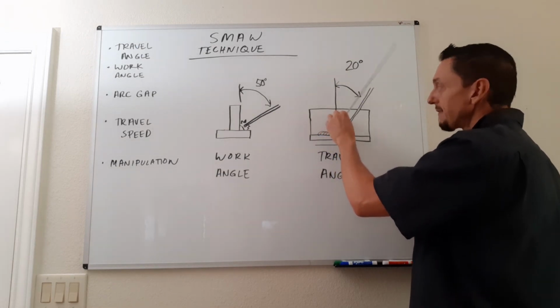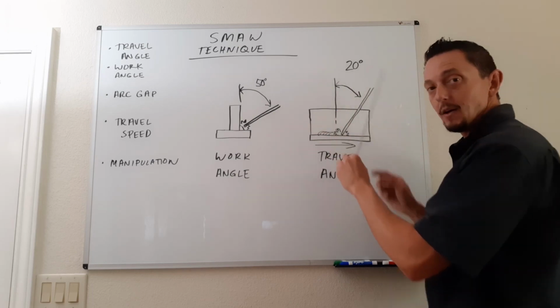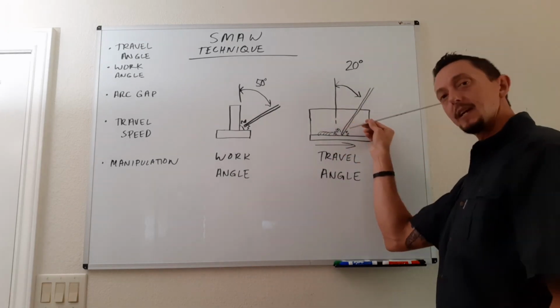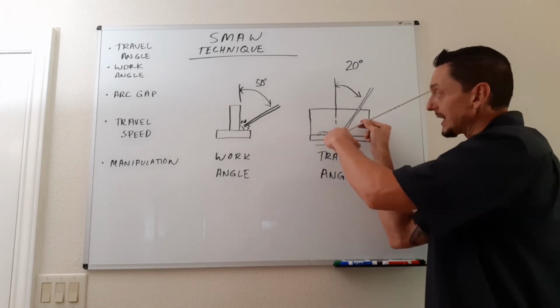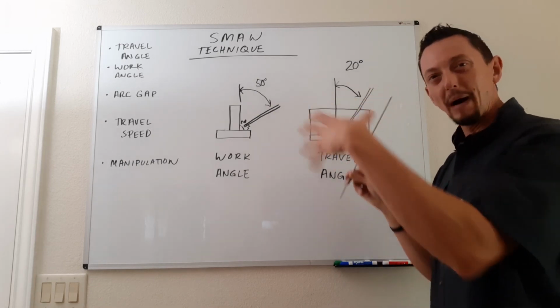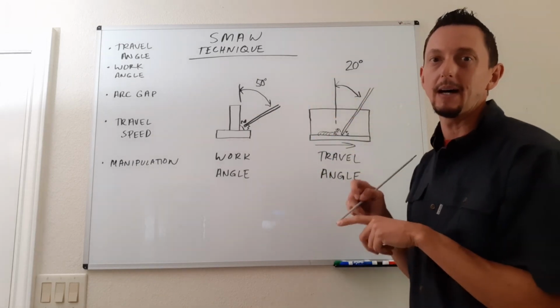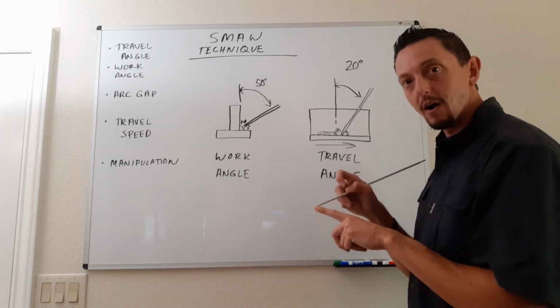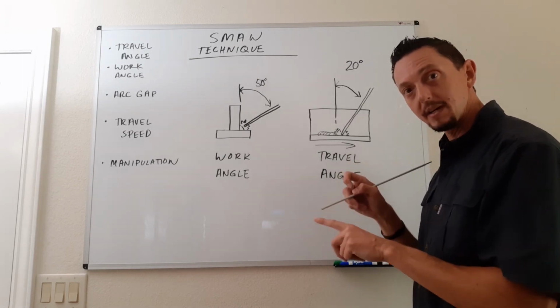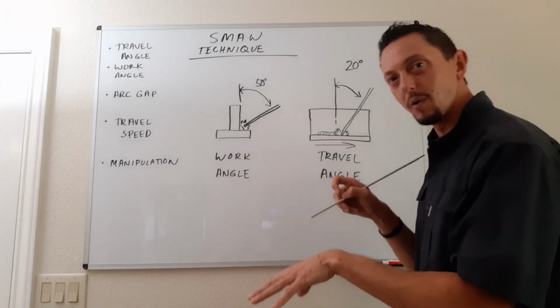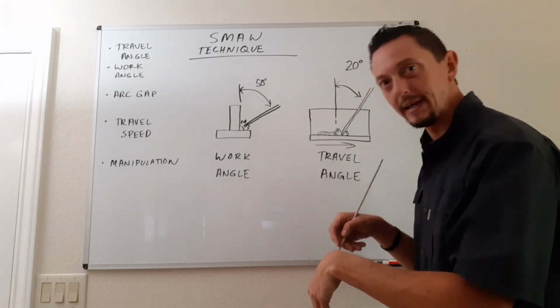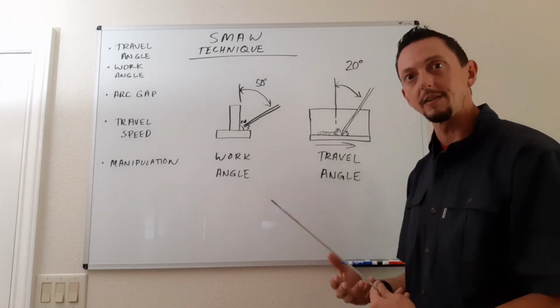Now, if we vary from that, if we get to the extreme over here, we're going to see that in our weld. We're going to get a higher, more kind of piled up weld because we're going to be directing the heat from the arc and the weld metal that's coming off the end here onto our weld metal rather than into the base material and really welding it all together, right?